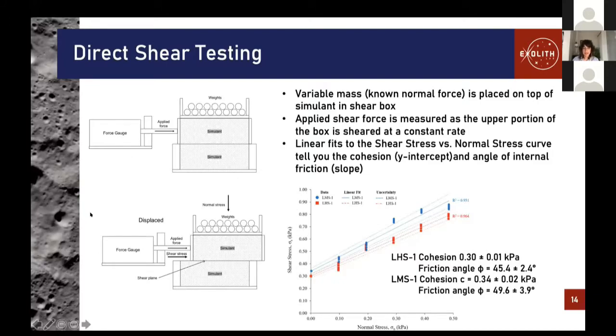If you're not familiar with this test, and I wasn't until relatively recently, being an observational astronomer, over the last few years I've learned more about this. The idea is that you have a shear box that has a top part and a bottom part, and you fill that box with simulant. The top part is disconnected from the bottom so it can move across. Then you load a variable mass representing a known normal force, some weight on top, to induce a normal stress, and then you apply a shear force along and shear off that top portion of the box.